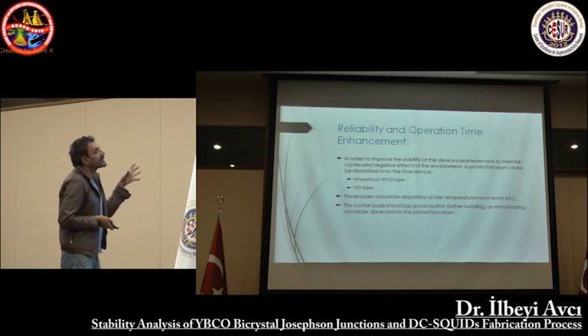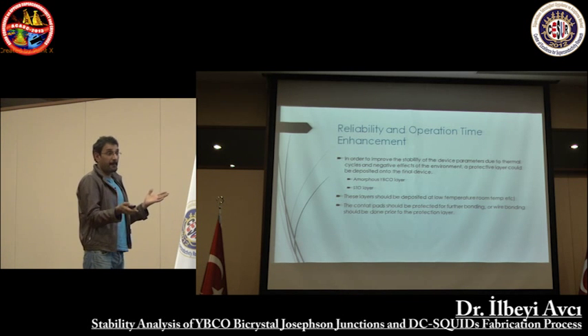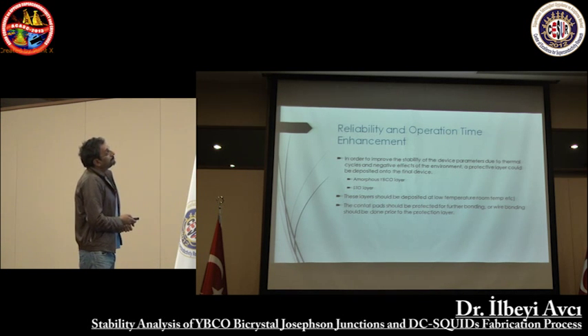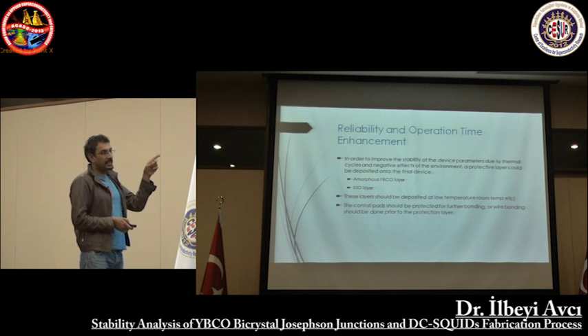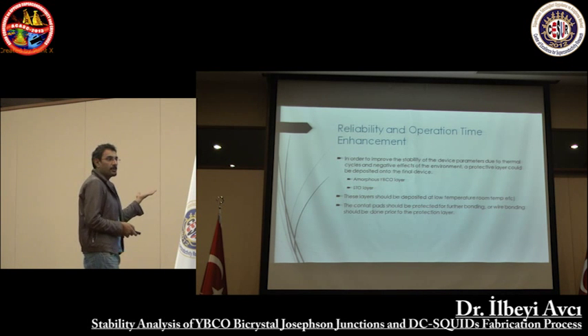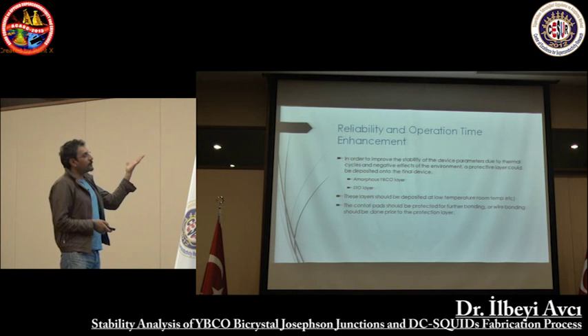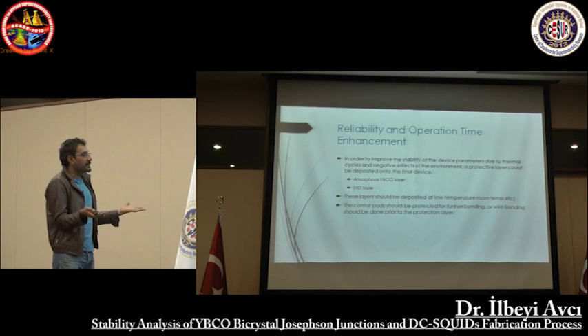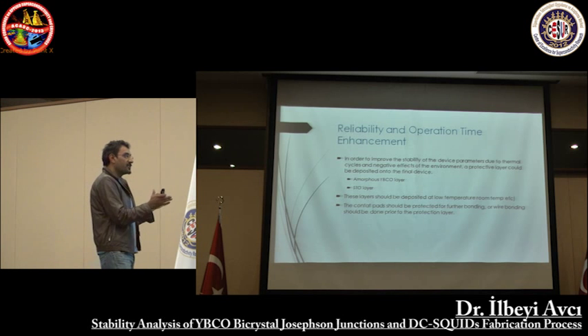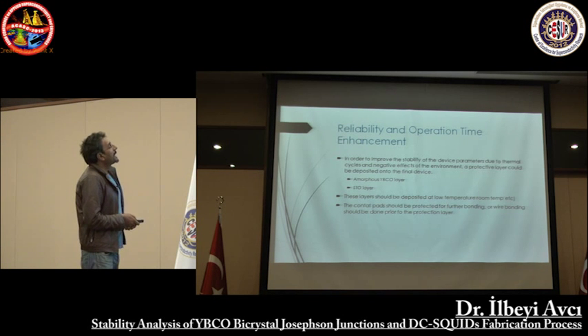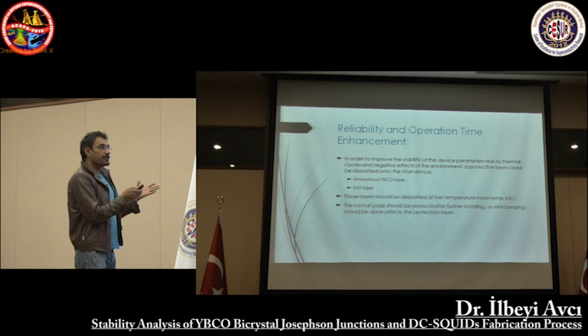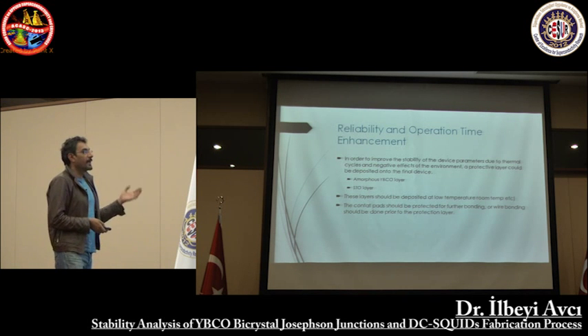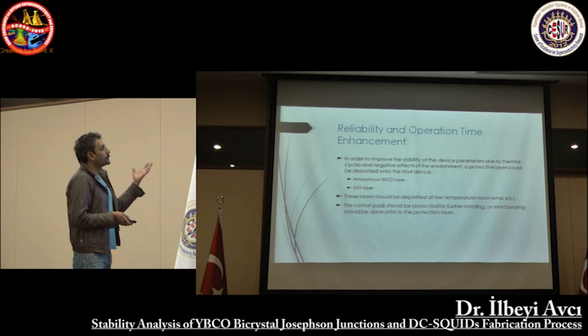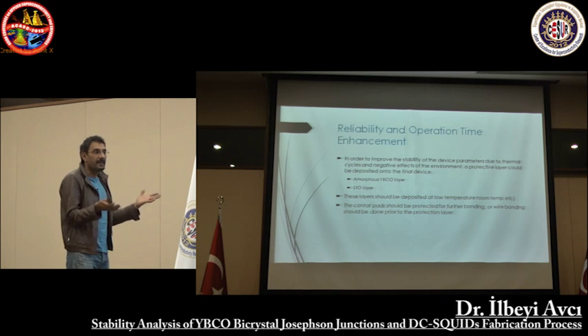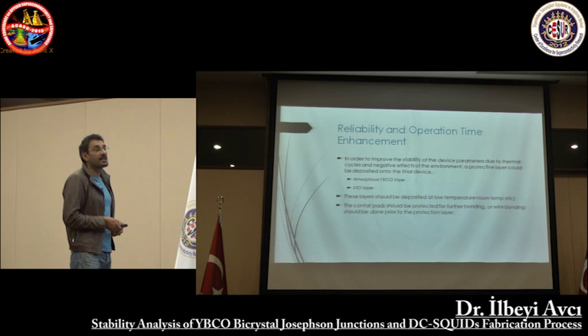The second part is the reliability and operation time enhancement. In order to improve the stability of the junctions over time, we applied two different layers. One of them is an amorphous YBCO layer. You can deposit the amorphous YBCO layer by room temperature deposition, because you have to protect the junctions from high temperature. The other one is the STO, strontium titanium oxide layer. This is a dielectric layer, and it behaves as a very strong protective layer for the junctions.